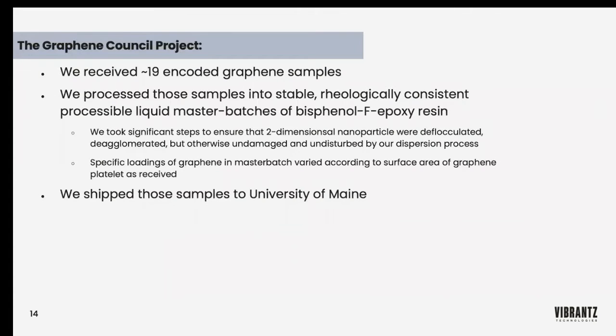So as it relates to this project, we received 19 encoded graphene samples. We processed them, and we didn't know exactly what they were. We just saw that they were samples, the little 50-gram sample. And we processed these samples into stable, rheologically consistent, processable liquid master batches in bisphenol F resin for the purpose of this study. We took significant steps in this process to make sure that we were deflocculating and deagglomerating, but not otherwise damaging the particles, and we processed them all on the exact same piece of equipment under the exact same parameters.